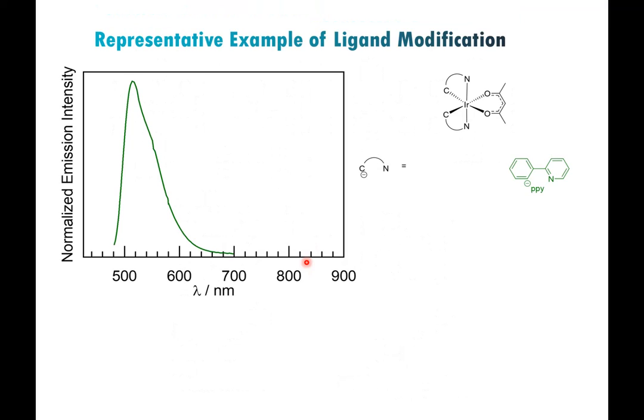All right, so again, something that I don't need to show the people in this room, but this is how the phosphorescence behavior works in these common cyclometalated iridium compounds. So this 2-phenylpyridine is the simplest, I suppose, of the cyclometalated ligands that's used. It was used in a lot of the earliest studies. And so when you have these types of compounds, the color of the phosphorescence is dictated by the choice of cyclometalated ligands. So the excited state is going to involve considerable metal to ligand charge transfer character with the iridium 5d orbitals being strongly involved in the HOMO, and then the pi star on the cyclometalated ligands being the orbital that you would promote the electron to in the excited state.